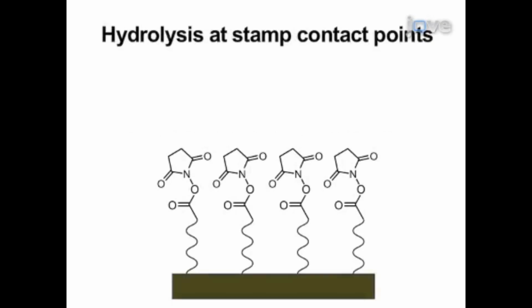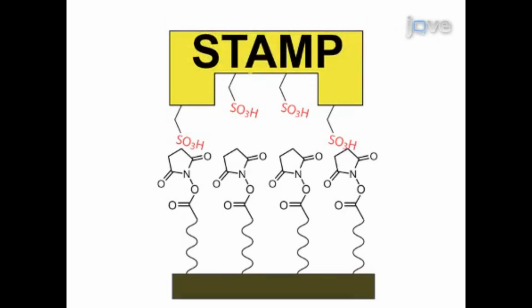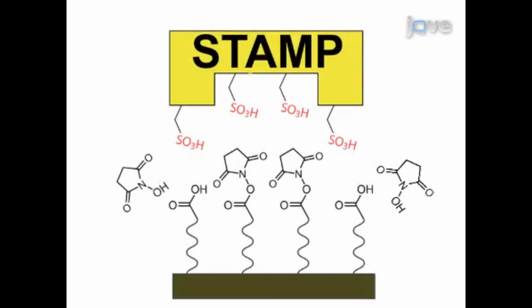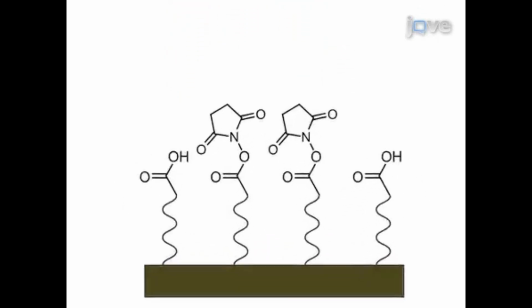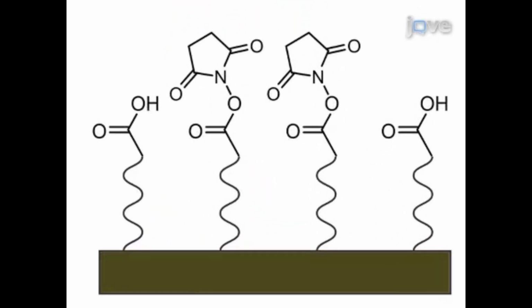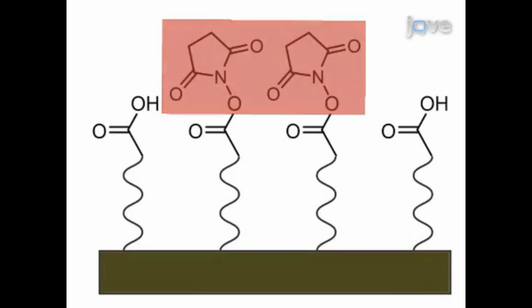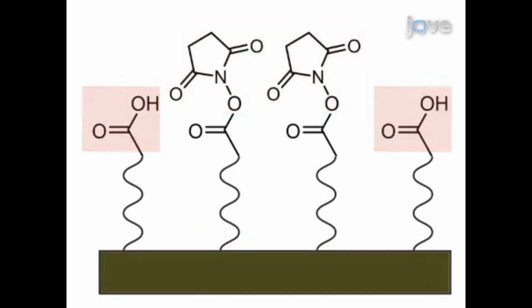Soft lithographic nano-patterning was used to create chemoselective patterns on oxide-free silicon and on germanium. The reaction between the NHS functionalized substrate and the catalytic pattern stamp leads to the hydrolysis of NHS moieties in areas of conformal contact, yielding a patterned bifunctional substrate bearing regions of NHS activated and free carboxylic acids.